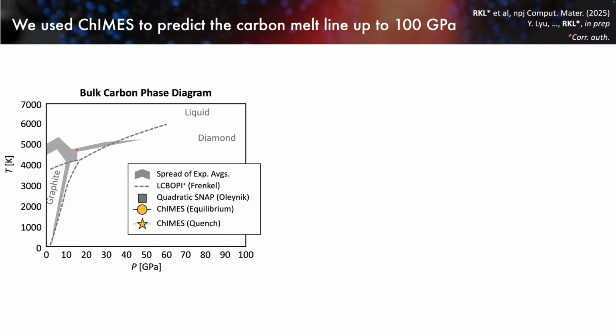What you get is the curvature of the slope of the melt line, and you shift it up and down until it seems like you get a result consistent with the expected triple point of the material. So there's a bit of finagling that goes into converting those experiments into a phase diagram, especially for the liquid-solid portion.